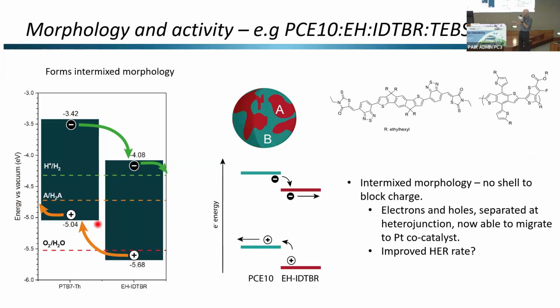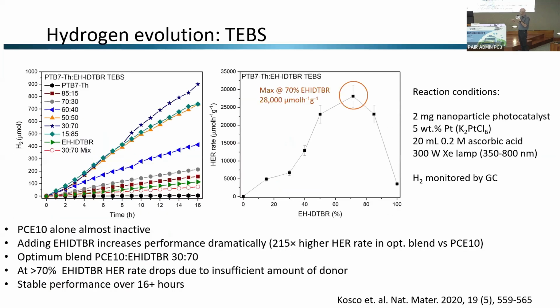Again, we've got this nice energetic offset. It's the same material set, so this is exactly the same. But now we have the opportunity for both electrons to find their way to the surface and holes to find their way to the surface. So we've got the best of both worlds here. And in fact, that's absolutely what we see from the HER rate. So you can see here, the maximum rate is when we have something like a 30-70 or even less ratio of the donor and acceptor.